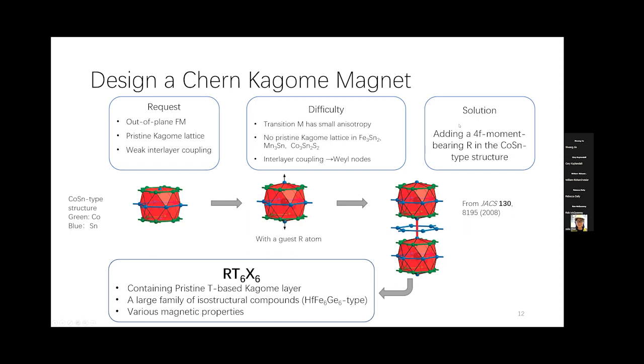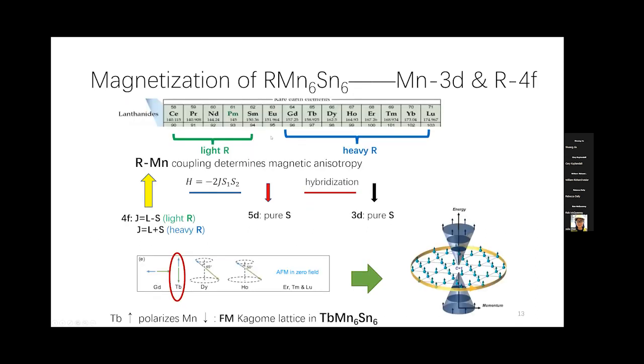So our solution is to try the other structure, the 166 structure. That means you are adding 4f local moment bearing rare earths in the cobalt-tin type structure. So this plot shows how we introduce rare earth atoms in the vacancy of the cobalt-tin atoms, and that rare earth will push the tin atoms up and down, giving you a doubled C-axis, giving you a very large family of 166 compounds. That is a very large family of isostructures and has various magnetic properties depending on the rare earth atoms and the transition atoms.